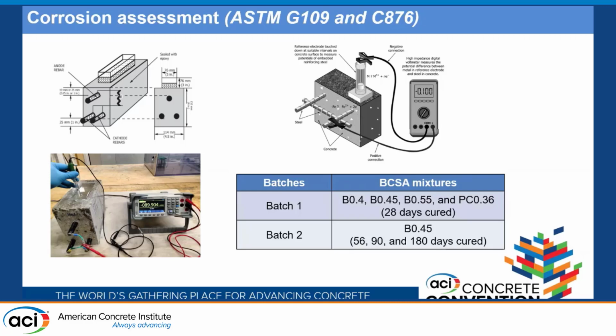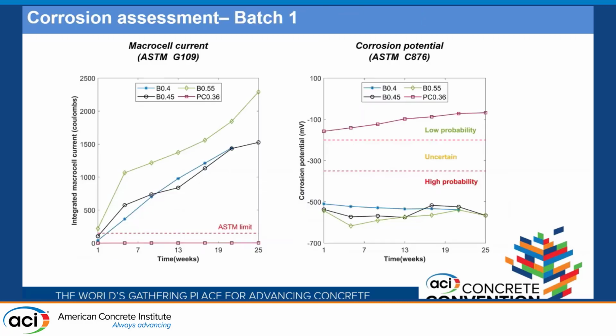And for this study, I've used two batches. The first batch consists of BCSA with different water cement ratio, but same curing period. And for the second batch, I've used just one water cement ratio of BCSA and then modified the curing period. Let's start with the results of batch 1.